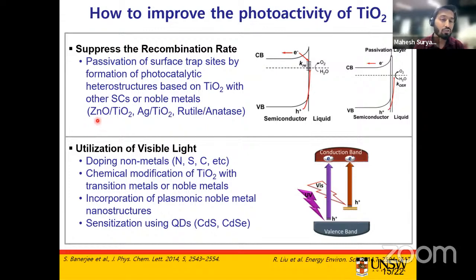You can see examples such as zinc oxide heterostructures with TiO2, metal heterostructures such as Ag with TiO2, or heterostructures of the rutile and anatase phases of TiO2. Also, we can improve the performance by utilizing visible light, because the band gap of TiO2 is very wide. That means it can only absorb light in the UV range, and is not able to absorb light in the visible region.